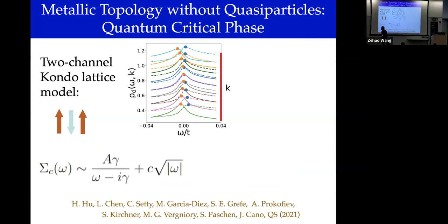And for the two-channel Kondo problem, there are some asymptotically exact low-energy forms of self-energy that were known, and our calculational method captures that. We also find that in the lattice model, there's this unusual and never suspected pole in the self-energy, and that was actually very important to produce these Kondo-like features, which are dispersing with a very large width. But as a characterization of non-Fermi liquid state, quasi-particles being lost, that's this particular form of self-energy.